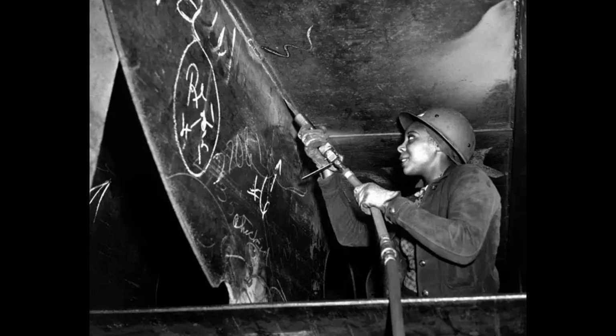The critical temperature for Liberty ship steel averages around 4 degrees Celsius. That is 40 degrees Fahrenheit. Ships operating in the North Atlantic routinely experience temperatures below this critical point. The hull steel transitions to brittle behavior. A small crack, perhaps at a stress concentration like a square hatch corner or a weld defect, begins to propagate. In a ductile material, the crack would arrest. In brittle material at low temperature, the crack runs.